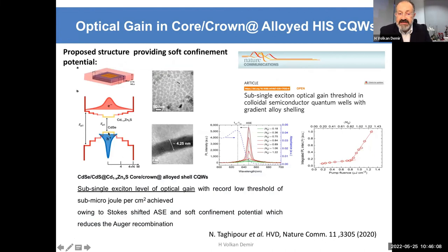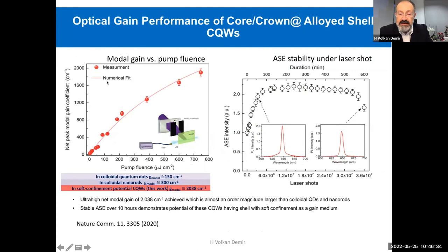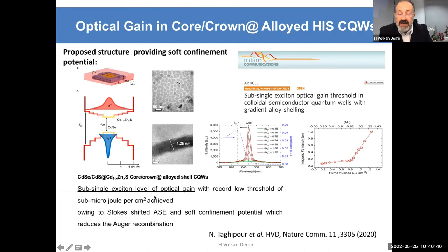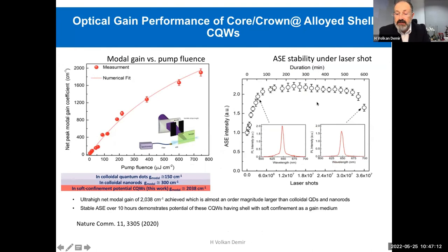And this is now more along the direction of quantum engineering, where we very carefully design the gradient barrier. So we start with the core, and we carefully choose what levels of barrier we will introduce in such a three-dimensional structure. This is basically a nanoplatelet in a box. It has core, crown, and shell. And this then gives us a very surprising result, which allowed us to reach sub-single exciton level optical gain. This is a record low threshold statistically per particle. Normally, we still are in the bi-excitonic gain regime, but in the ensemble, we can reduce the overall population inversion point so much that per particle, the average happens to fall into the sub-single level.